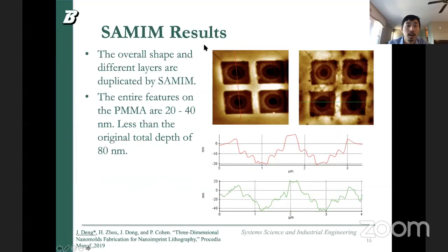So here I'm going to show some results. The overall shape and different layers are shown here. Because this was a manual process that I tested, the results are not as good as the original nanomachining process using AFM, but it's quick. It shows clearly a few layers, and the entire feature is around 20 to 40 nanometers, less than the original total depth of 80 nanometers. And it is a subsequent application for fast stamping on different substrates. You can read more about this result by searching for this paper here.